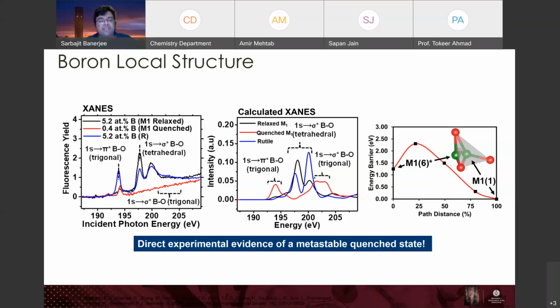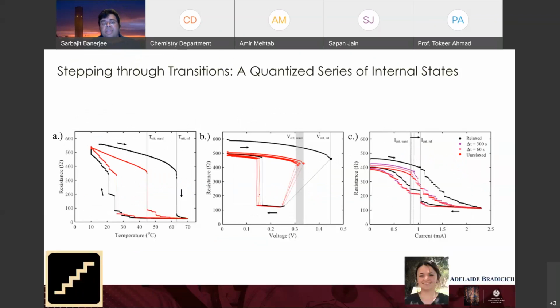This provides direct experimental evidence of a metastable quench state and the evolution of the state as a function of temperature. And this can be used very directly to build memristors, showing a series of steps. These are analog devices where the exact state of the system depends on what has happened to it in the past. This is work by Adelaide Bradicich with Dr. Patrick Schamberger. I'm going to play a little video that we made on this.